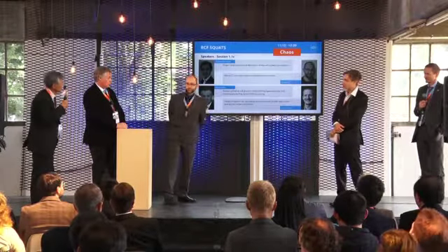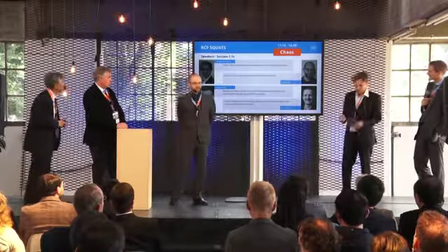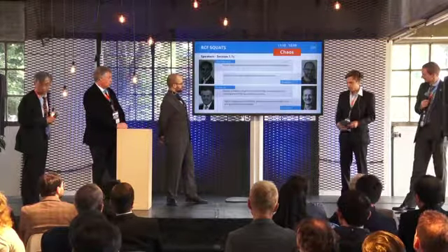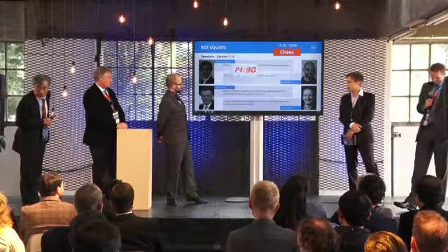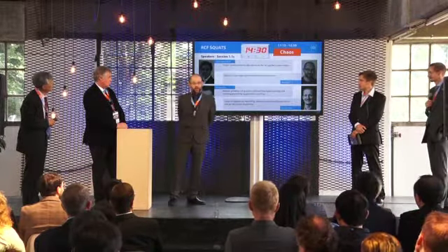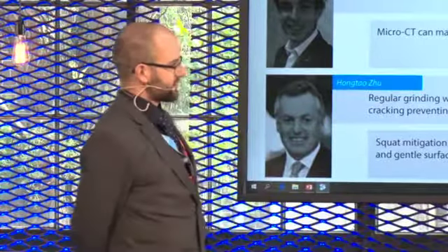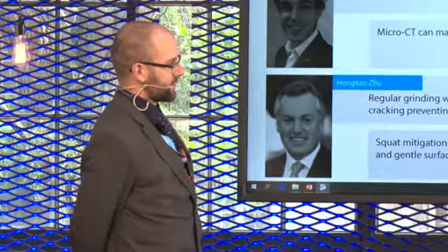Okay, thank you very much. And then regarding micro CT, so the largest sample that we actually tried to get through was around about 10.5 centimeters, which is a lot of steel because obviously steel is very, very dense, which is why typically you don't try to X-ray it. So it actually performed an awful lot better than we initially expected.